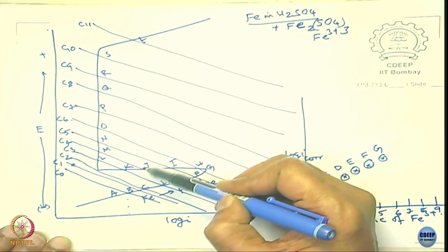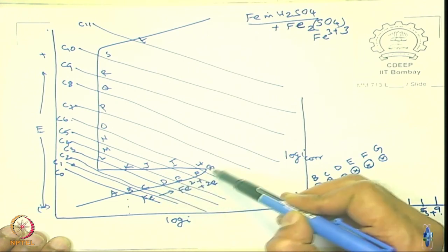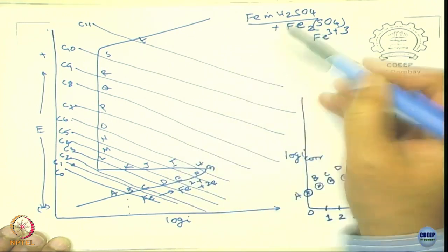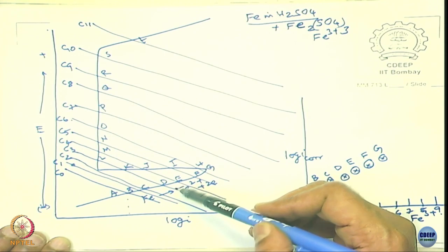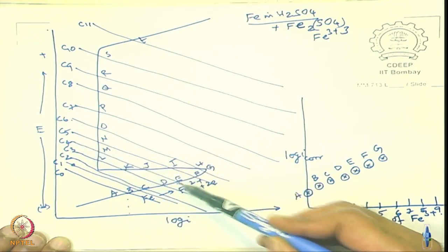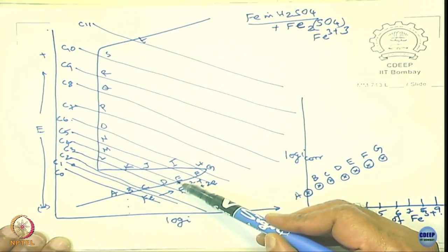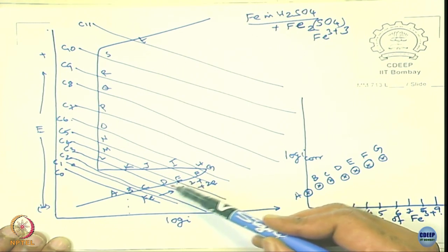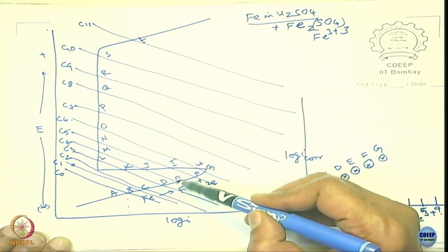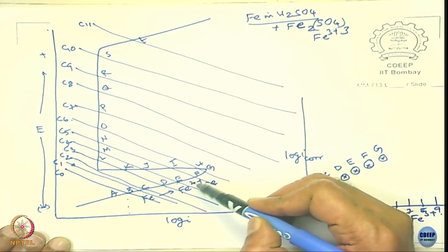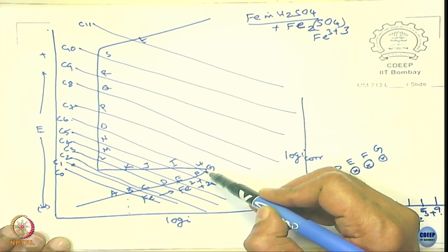or to reach this particular point, the system has to cross this critical current density. So, when I add these ferric ions, it will not cross. For example, if you add C4, C4 corresponds to this, it cannot go beyond E. So, the corrosion rate only increases from D to E, it would not reach J. Neither would it reach M. Okay. So, it can go only up to this. So, when adding higher concentrations, the current increases, it does not go beyond these values, but when you add, let us say